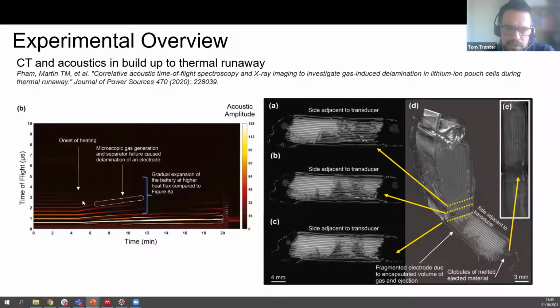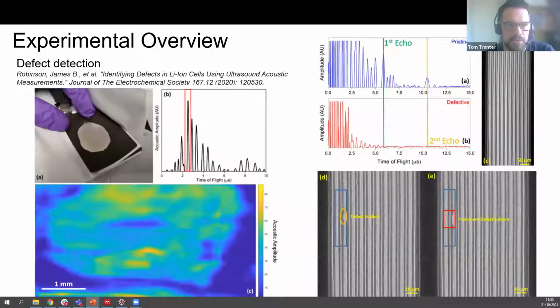The acoustic technique is much more sensitive than the eye is, and also than the temperature sensor, because if this runaway event and this gas production is happening in the center, the acoustics is going to be able to pick that up straight away, whereas it takes a little time for heat to propagate out and affect the surface temperature. So it's like an enhanced safety feature that you might be able to use acoustics to do this sort of runaway monitoring, and hopefully we'll be able to build on this and show more work in the future related to that.